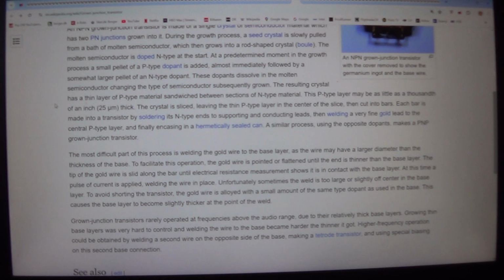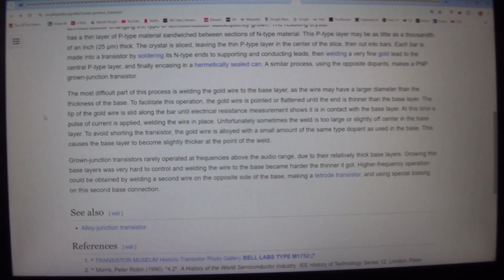The most difficult part of this process is welding the gold wire to the base layer, as the wire may have a larger diameter than the thickness of the base. To facilitate this operation, the gold wire is pointed or flattened until the end is thinner than the base layer. The tip of the gold wire is slid along the bar until electrical resistance measurement shows it is in contact with the base layer. At this time a pulse of current is applied, welding the wire in place. Unfortunately, sometimes the weld is too large or slightly off-center in the base layer. To avoid shorting the transistor, the gold wire is alloyed with a small amount of the same type dopant as used in the base. This causes the base layer to become slightly thicker at the point of the weld.